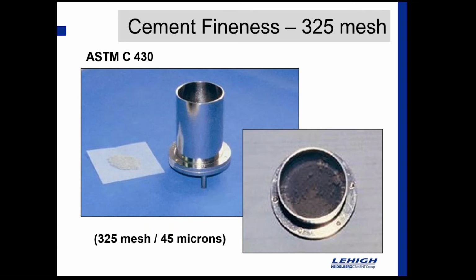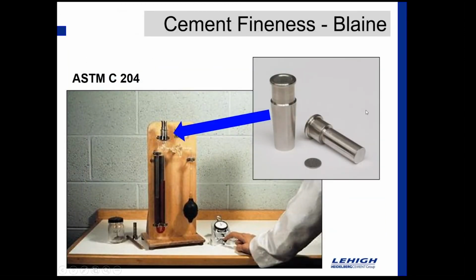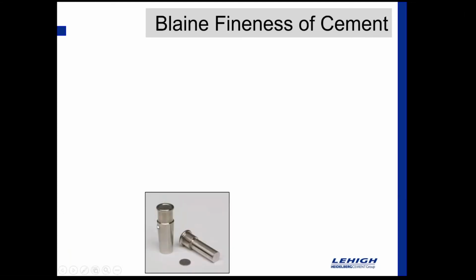So it's an extremely fine screen. If you poured water into that screen with no cement, the water wouldn't go through that screen. That's how tightly woven the screen is. So you have to have a high pressure nozzle to actually wash this material with. You're kind of blowing the fine cement through there, and you're looking at the amount retained. That's going to give you an idea of the overall fineness of that cement. We can also measure that same fineness by looking at the Blaine. That's ASTM C204. And this is the container here, this middle picture, that you would place your cement sample in to drop it into the Blaine surface apparatus.